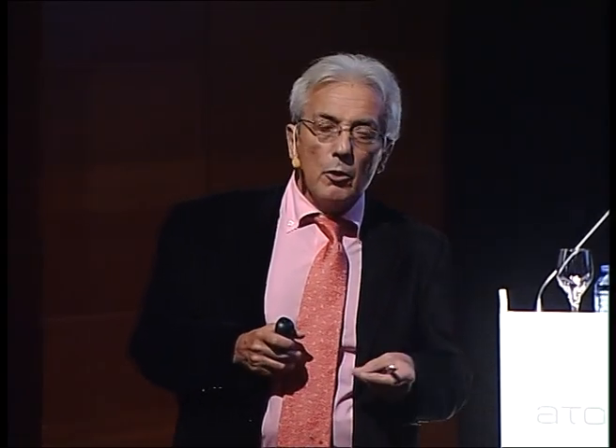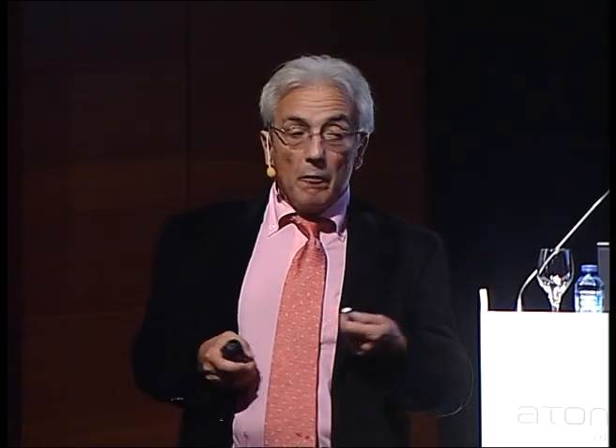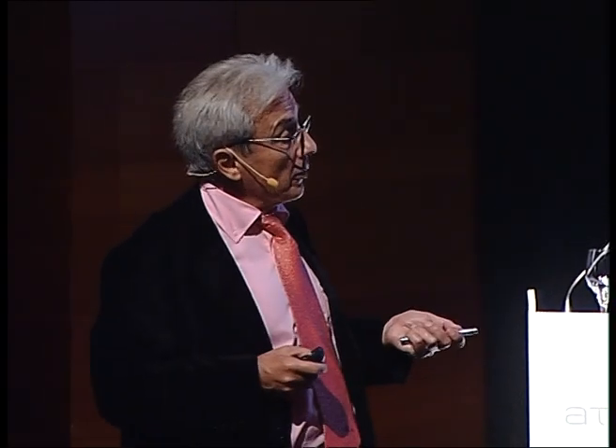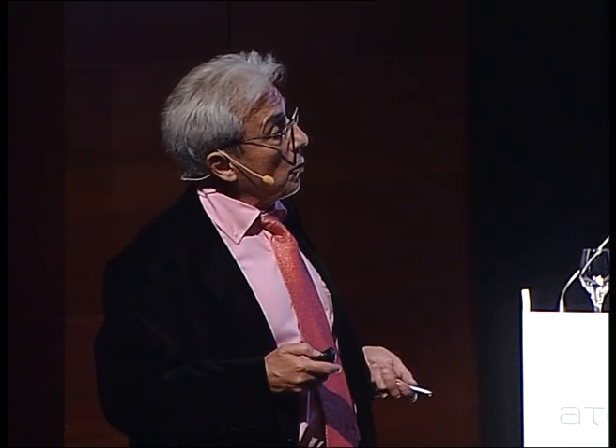One of the ways, in fact, is by introducing very different spin relaxation times in the two magnetic layers. If one looks at the transport equation, it is possible to distort completely the distribution of spin accumulation in the structure, and so finally to distort completely the angular dependence of the torque, and to obtain a very different behavior from the standard behaviors that I described, and finally oscillation at zero field. I don't want to discuss this point.